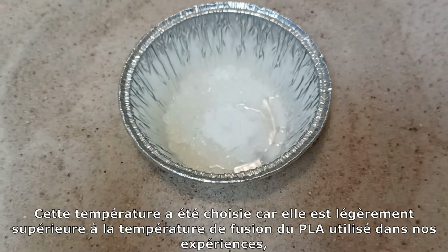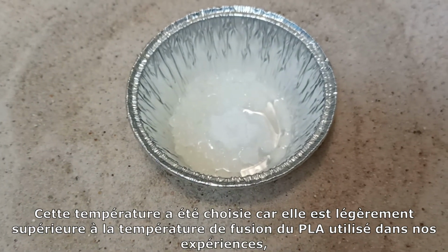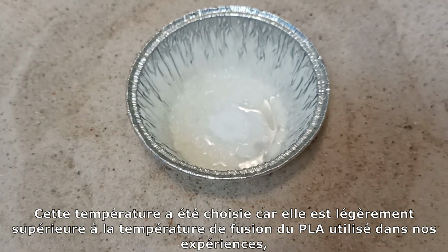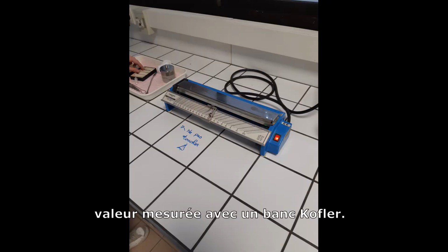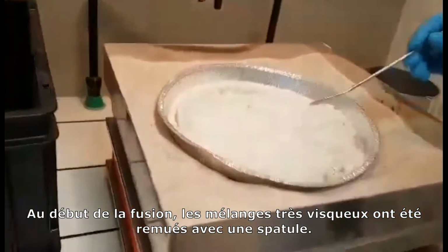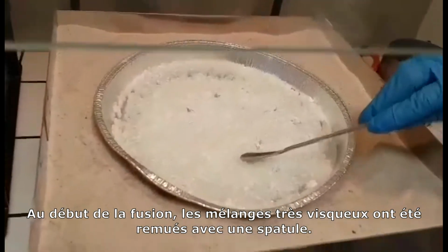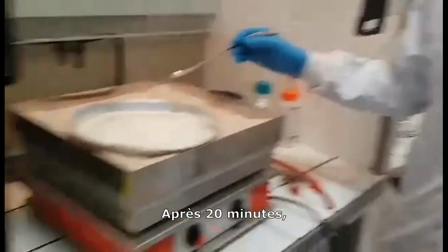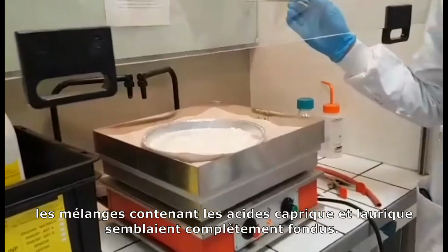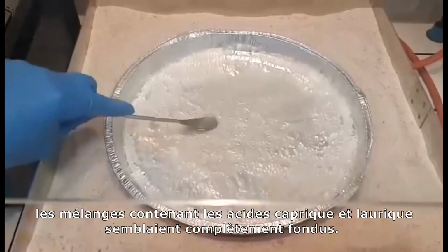This temperature was chosen as it is slightly higher than the melting temperature of the PLA used in our experiments, a value measured with a Kofler bench. When beginning to melt, the very viscous mixtures were stirred with a spatula. After 20 minutes, the mixtures containing capric and lauric acid seemed fully melted.